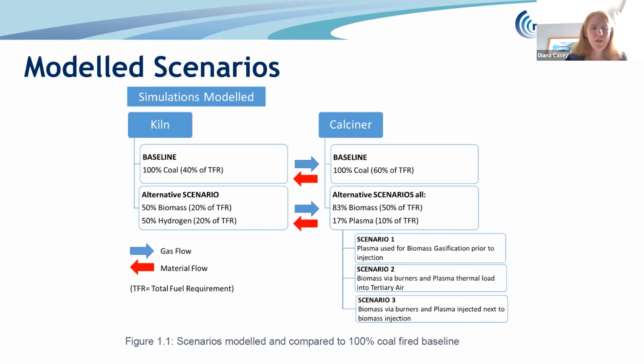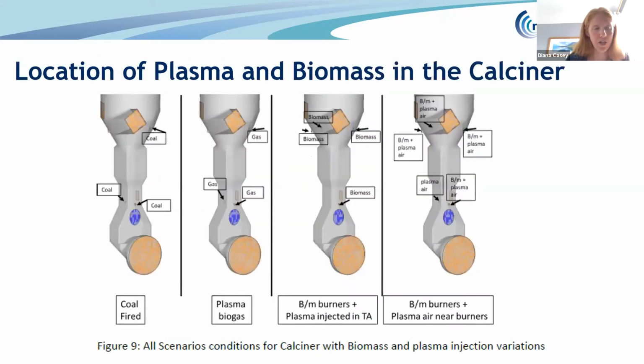So this diagram shows different scenarios that were modelled. For both the kiln and the calciner, there was a baseline scenario which used 100% coal. And then for the kiln, there was just one scenario, which was a 50% hydrogen, 50% biomass mix. For the calciner, we used a ratio of 83% biomass to 17% plasma, but the unknown quantity of that plasma meant that 3 different options were put forward for how it was used to inject heat into the calciner. And those scenarios are much easier to describe with a diagram, which I've got here.